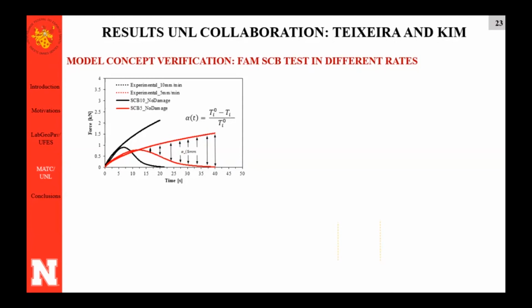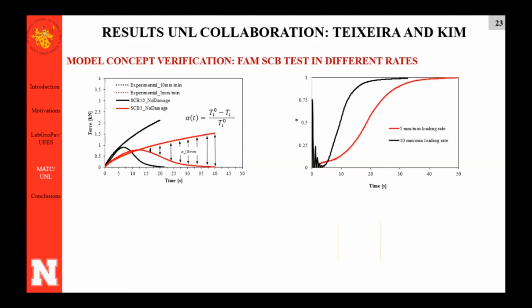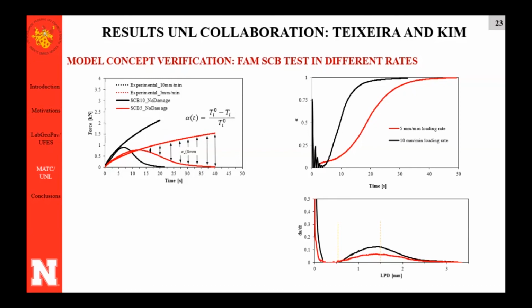So I calculate the alpha as a function of time, and we got this curve. Basically alpha goes from 0 to 1, and 1 is when we have complete separation. And we calculate alpha dot, the rate of damage propagation. And you can see the shape of the curves. It follows, not perfectly because this is experiment, but it follows a Gaussian distribution. And it's independent of the rates.